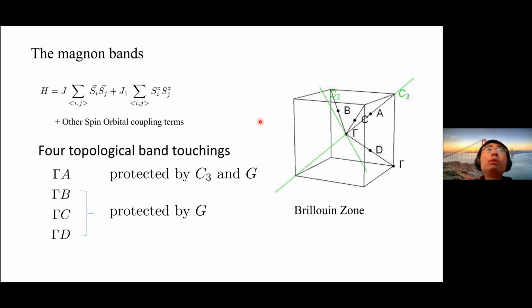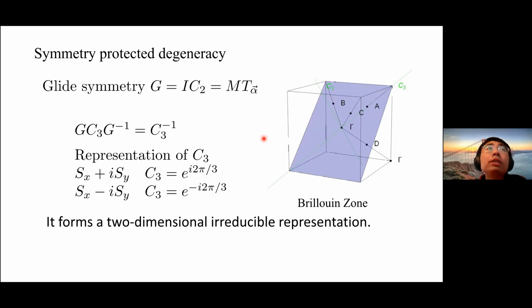Let me give you some idea about why we have these symmetry protected band touchings in the system. The idea comes from the representation theory of the symmetry. For example, if we think about this glide symmetry - the glide plane is a combination of mirror reflection and translation from one side to the center of this cube, where this translation is half of the Bravais lattice translation - what you can easily see is that the glide symmetry does not really commute with the 3-fold rotational symmetry.